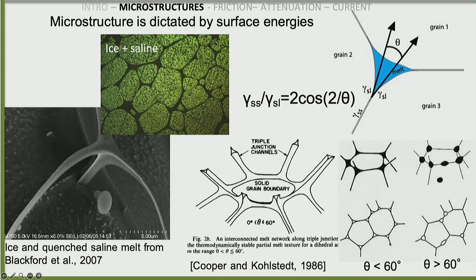Incidentally, this less than 60 degrees angle has been determined in every binary system that I've ever looked at, and I've been trying to make my way through all the different systems. I'm sorry, not every binary system, every binary with ice system. So various salts and acids have this low dihedral angle, which, by the way, is similar to what you have for olivine plus melt. So again, making our work relevant, with crosstalk between the different worlds. And since this is supposed to be a mechanical control, our view of the world is that we can use one system, and it's analogous to other systems that have this same kind of microstructure.